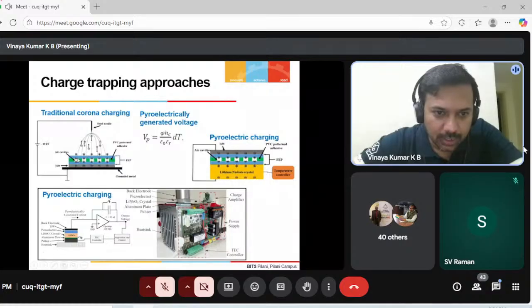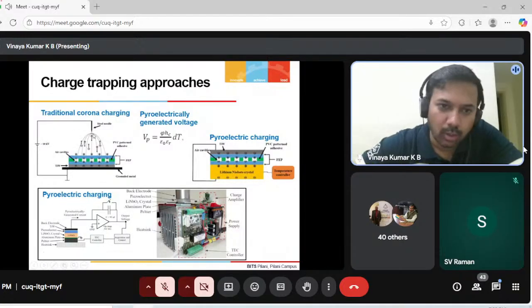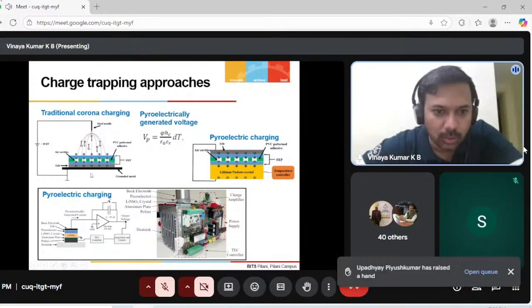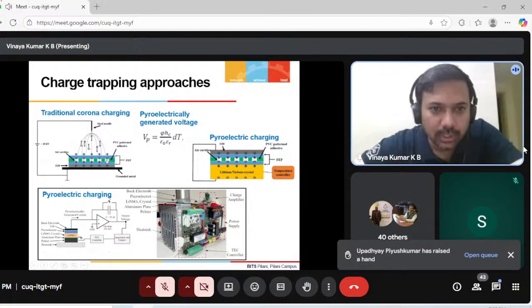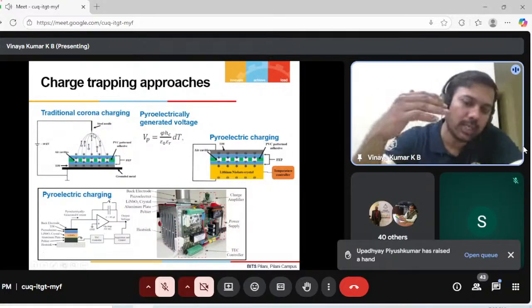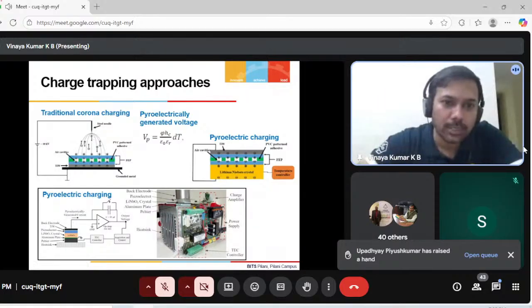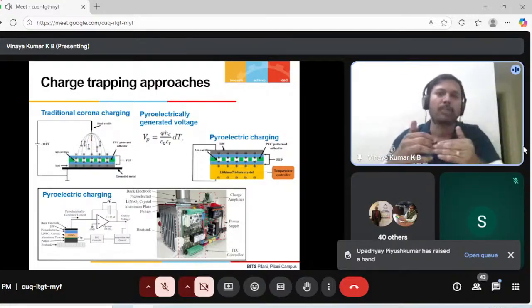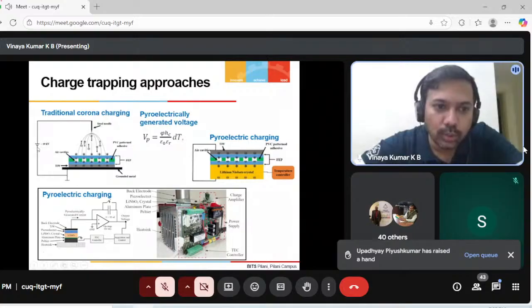In the corona charging method, you have the voids, and you have a steel needle of very small diameter. You apply a very high voltage for a very short time, and you break down the molecules. It converts them into positive and negative charges. All these charges get trapped here, because you are also applying a reverse potential on the ground. This is the well-known method, and it is used in many applications. But the problem is that you need a very sharp tip, and with several uses the tip burns and is no longer as sharp as before, right? Also, you need a high voltage.